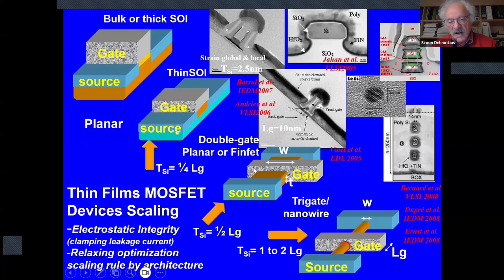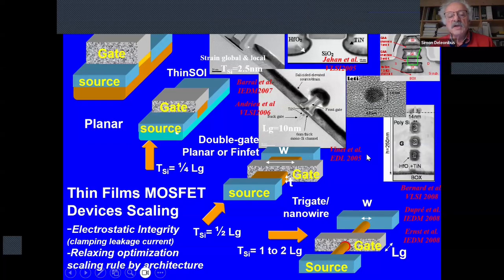And as you scale down and add an increasing number of gates, you can end up with something which looks like a nanowire or a nanobeam with an infinite number of gates. That's what people call a gate-all-around structure. So you can see here some TEM micrographs that we have been using in our publications since, you can see, as early as 2006, we proposed all these architectures that I've shown you by using thin films.